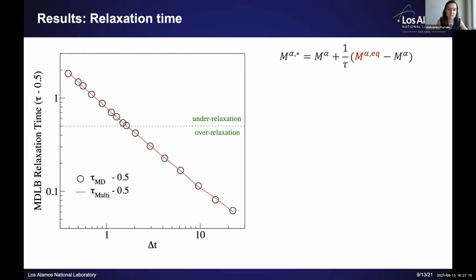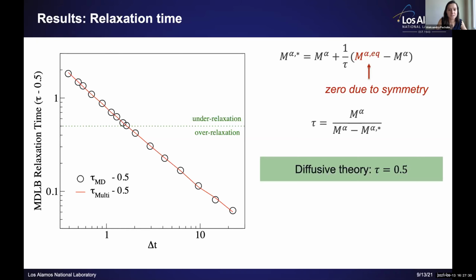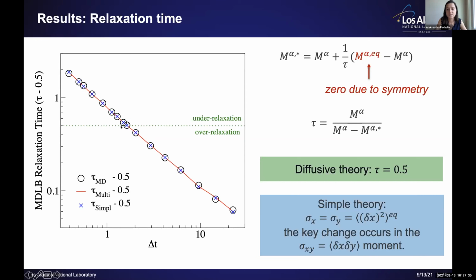This is the relaxation time from the MD and the relaxation time from the multivariate probability distribution function with the MD moments. They have perfect agreement. And again, here you can see that the transition happens at 1.6. Interestingly, the diffusive theory only has over relaxation, so our relaxation time is only equal to 0.5.